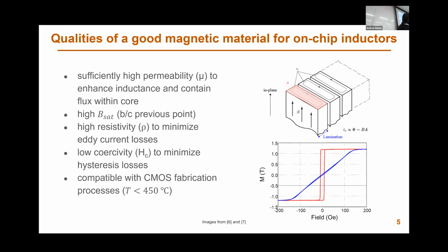The other contribution to core loss is hysteresis, which is just the area inside your MH or BH curve. And generally you want this area to be as small as possible. So low coercivity, low remanence, all that. And specifically for the case of on-chip integrated inductors, we want something that's compatible with CMOS, which means that we're limited to fabrication techniques that are low temperature, below like 450 degrees C.